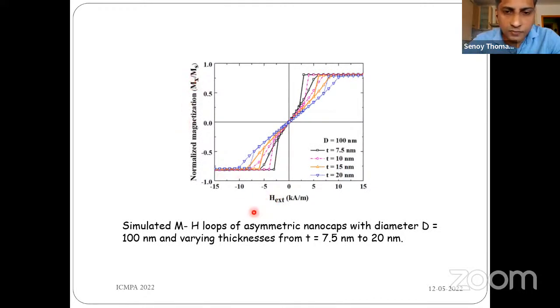magnetization in the X direction as a function of the external field, then one could see that if you keep on decreasing the field, at a particular intermediate field there is a drastic reduction in magnetization and negligible remanence and coercivity. And at very high field, the system is saturating in the opposite direction.